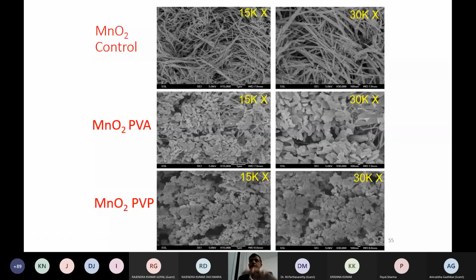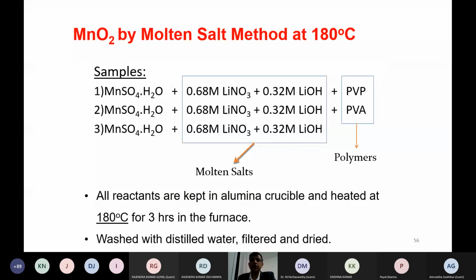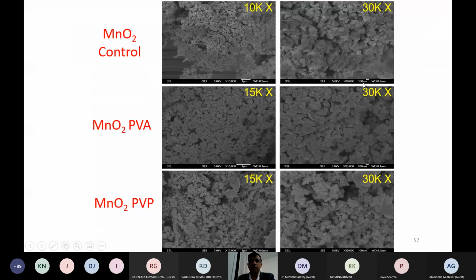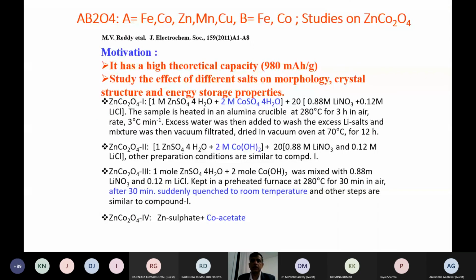So depending on which composites you want to make, you can design accordingly. Remember the temperature is 180 degrees, and at that temperature everything becomes spherical. You have to be careful: depending on the molten salt and temperature, we can see the difference in the morphology. Another one is the spinel-containing samples. You can try to prepare the sample by using the salt.